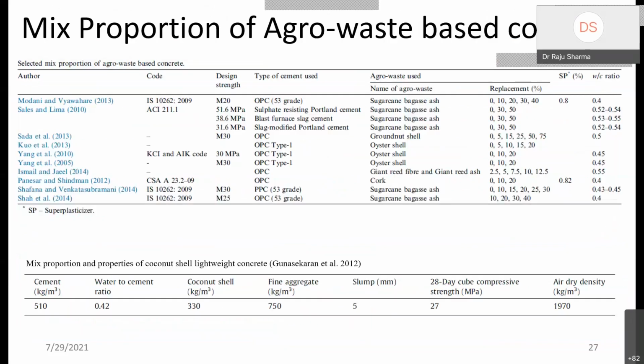Now, if you go with the replacement proportions, many people did. They have done with the different codes. You have Indian Standard 10262. Now the new code has also arrived in this design mix, and there is an American code also. There is a Korean code also. There is a Canadian code also, right? So people developed with the different design strengths, M20 to 51.6 MPa, and different strengths you can achieve through this particular replacement level and type of cement used.